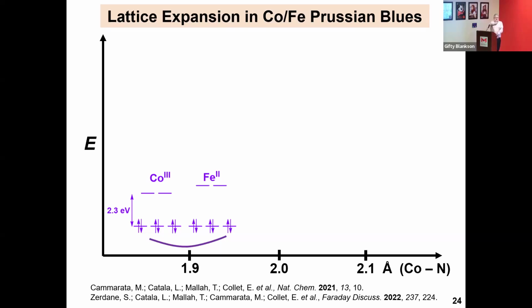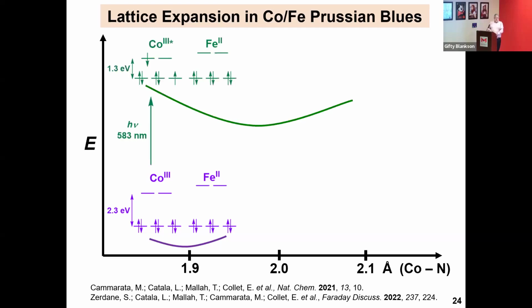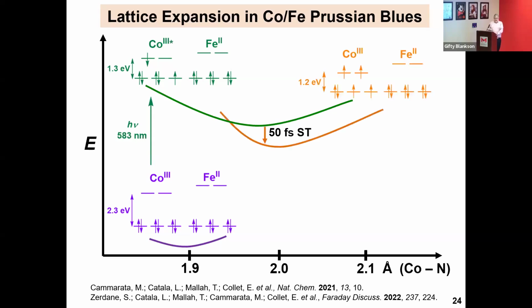You have these low spin cobalt-3 iron-2 pairs. Shine light on it. You quickly generate an excited state cobalt-3, keeping the iron-2 in the same electronic state. So all you did was remove an electron from the non-bonding t2g set and put it in the eg antibonding set. This quickly relaxes to give a new state where you have a high spin cobalt. Notice now you have, instead of one unpaired electron up here, two in the antibonding orbital and two down here. Iron-2 has not been changed, so this is prior to electron transfer.